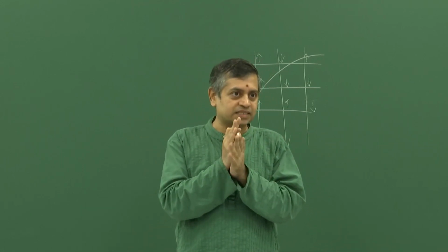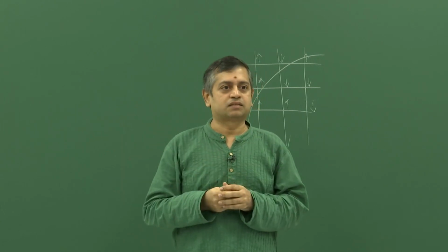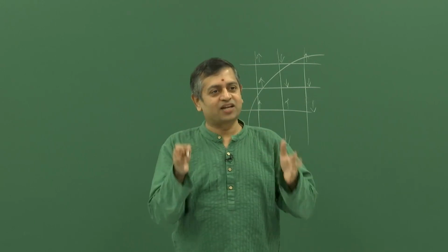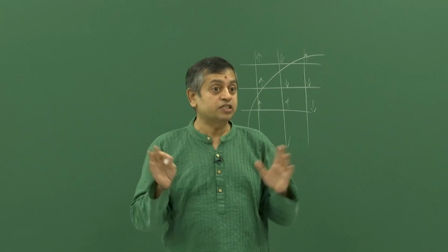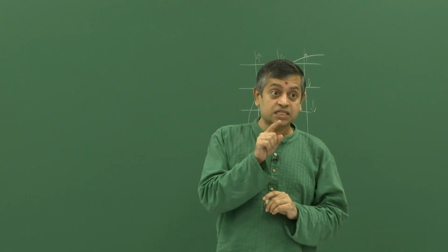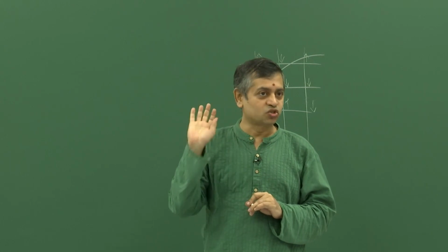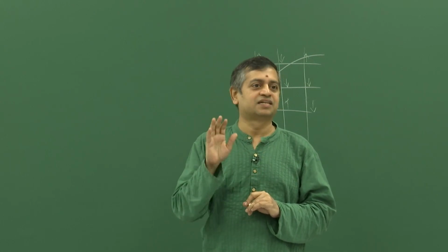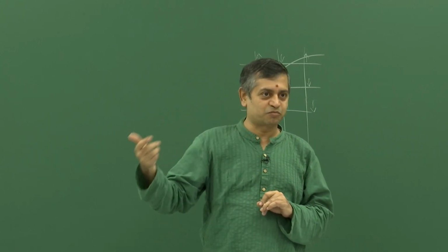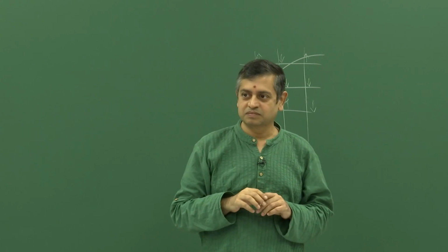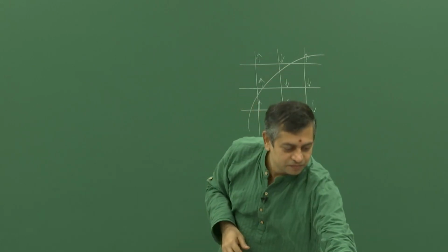So, to that extent, yes, we cannot claim that it will capture that, but if you know that, and you say no, these are not the first order effects for me, that much you will capture. But recrystallization is still a tricky problem, right. There is no nucleation here, there is no strain here, it will not be driven by, we are not saying which grain has higher strain compared to which grain. And the only driving force is the curvature.